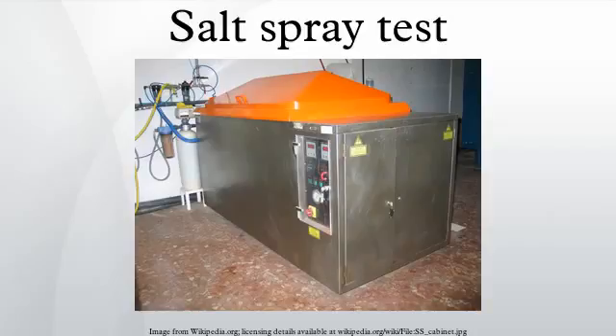1.0 hour exposure to a continuous indirect spray of salt water solution, prepared in accordance with the requirements of the test standard and acidified by the addition of acetic acid. This spray is set to fall out onto the specimens at a rate of 1.0 to 2.0 ml/80 cm²/hour, in an ambient chamber temperature. This is followed by 1.0 hour exposure to an air-drying climate, in a chamber temperature of +35°C. The number of cycle repeats, and therefore the test duration, is variable.